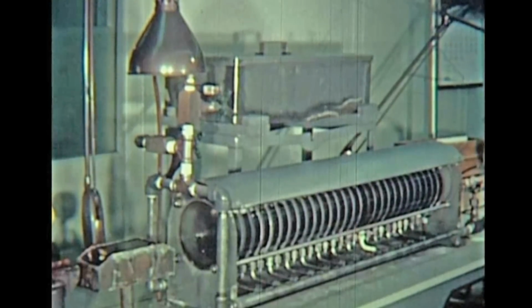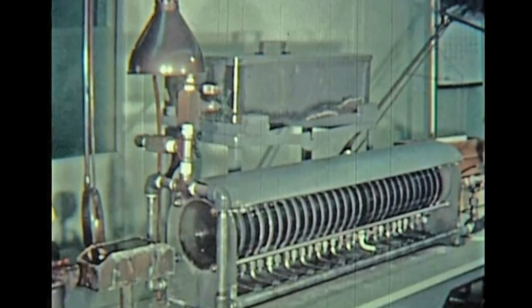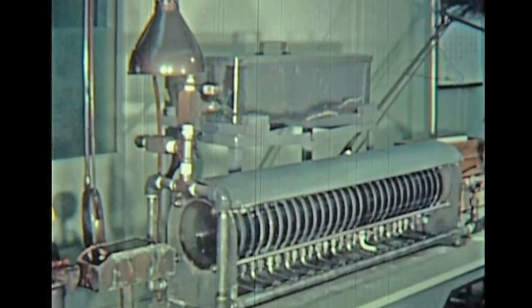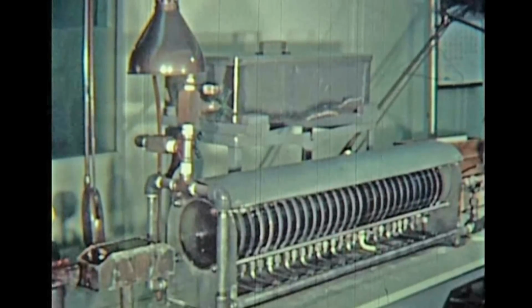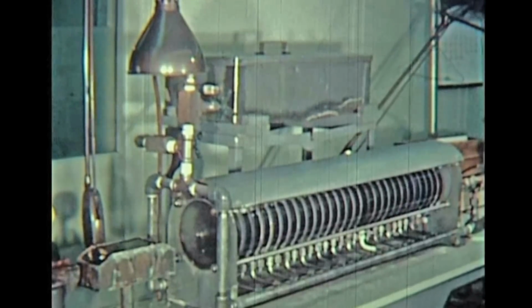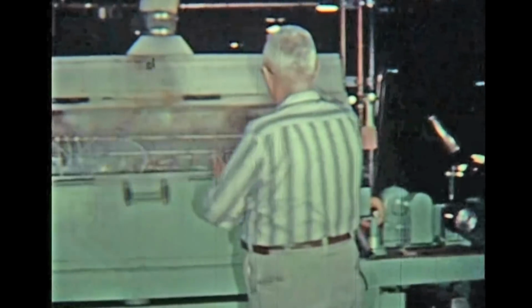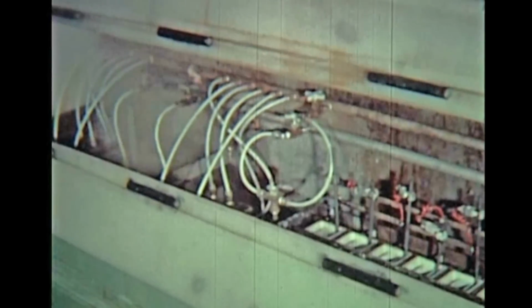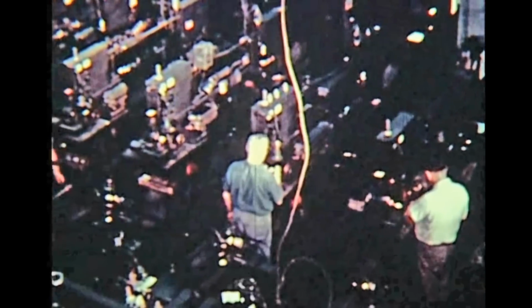For applications requiring wire smaller than the end of our normal drawing line, we use an electrolytic etching process. We have made wire as small as 50 millionths of an inch in diameter. This same process, slightly modified, is used for removing the lubricant for cleaned wire applications. If annealed wire is desired, we apply heat and tension in a hydrogen atmosphere and make annealed wire, which is also cleaned and straightened in one pass.